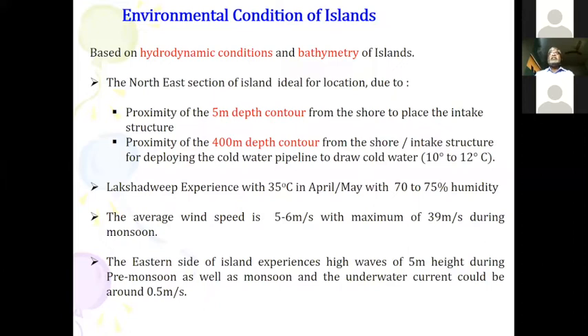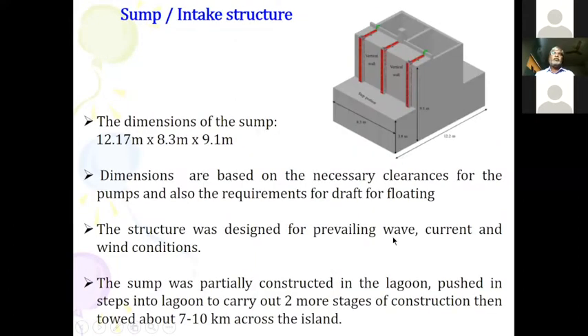You will have 35 degrees surface water with humidity of 70 to 75%, and an average wind speed of about 5 to 6 meters per second, with a maximum of 39 meters per second during the monsoon. The wave load taken for this particular design is about 200 kilonewton per square meter, and the wave height was a maximum of about 5 meters in the pre-monsoon and 5 meters during the monsoon. These are the data that have been collected for the design aspect of it.